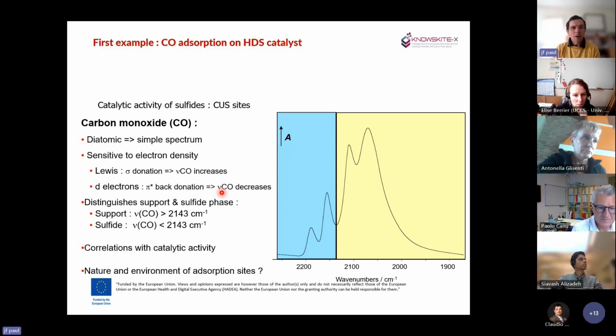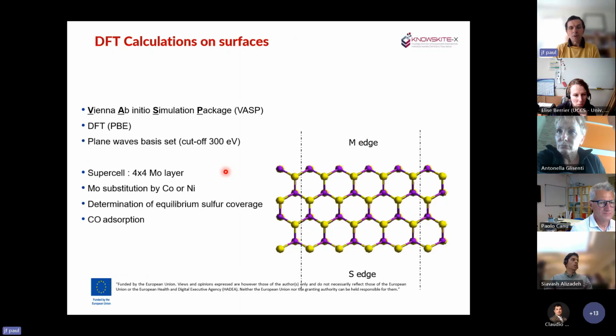I will give you some examples of what can be done. It's calculations that we have done in the lab some time ago. This is an example. It's an adsorption of a molecule on a catalyst, and the catalyst for the hydrodesulfurization is molybdenum disulfide. And the interest is that it's easy to adsorb CO and to get the spectra of CO on this type of system, and to try to use the CO as a probe molecule to define what are the active sites of this catalyst. So if we want to do calculation, we need to build a model.